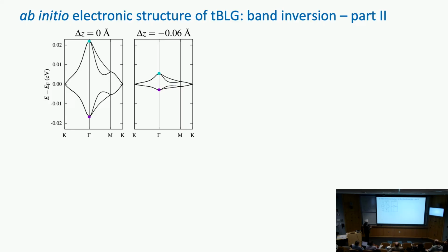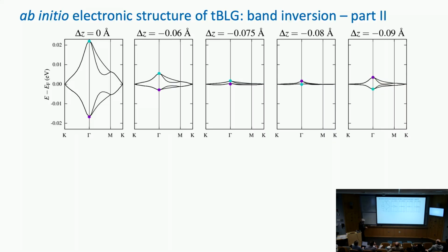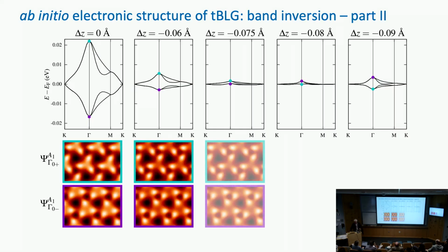These are the bands, and the flat bands only. I'm not showing you the rest. And notice that I'm showing you a very expanded range here. So this is 10 milli electron volts. This is 20 milli electron volts. So these are very flat bands indeed. And as you compress the layers, they become even flatter and flatter. And the two dots that I have shown you here in cyan and purple, again, as you increase the compression, switch positions again.